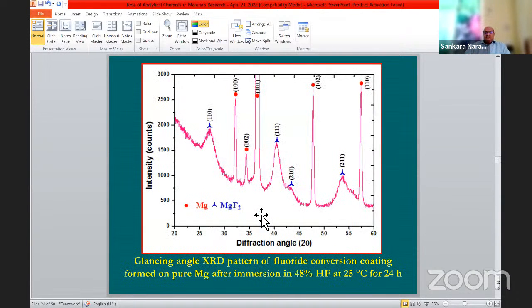I have deposited a fluoride conversion coating on magnesium. How do we prepare it? We take a magnesium sample and put it in 48% HF, concentrated HF, at room temperature for 24 hours. This is the way we develop a fluoride conversion coating. Normally magnesium is highly reactive, and if you put it in acid, it will undergo rapid corrosion. The only exception is if you put magnesium in concentrated 48% commercial grade hydrofluoric acid. There will be hydrogen evolution only for a few seconds.